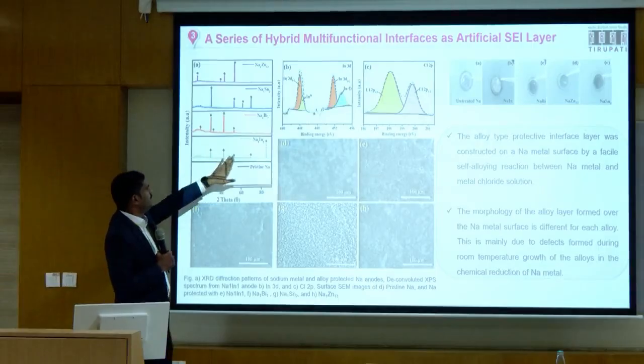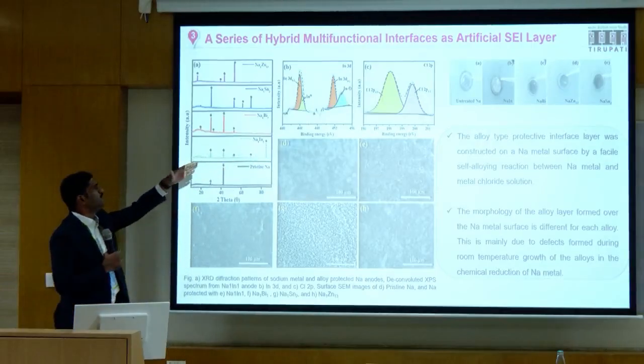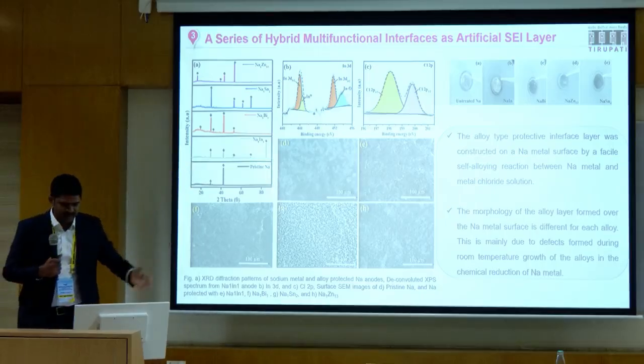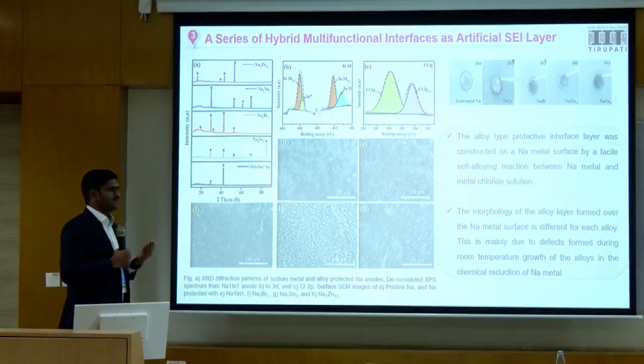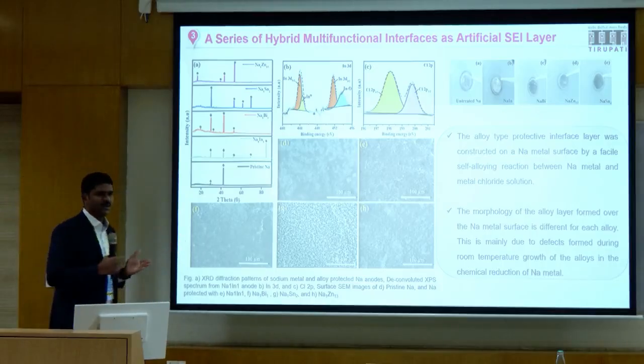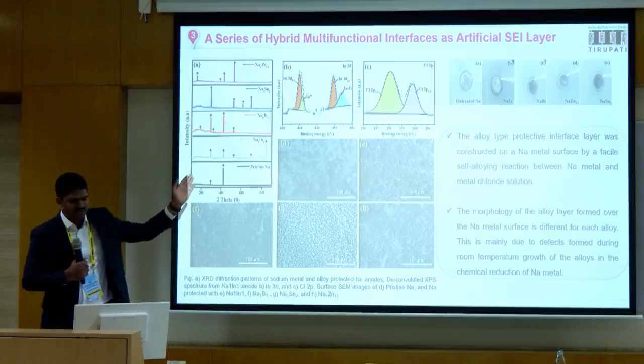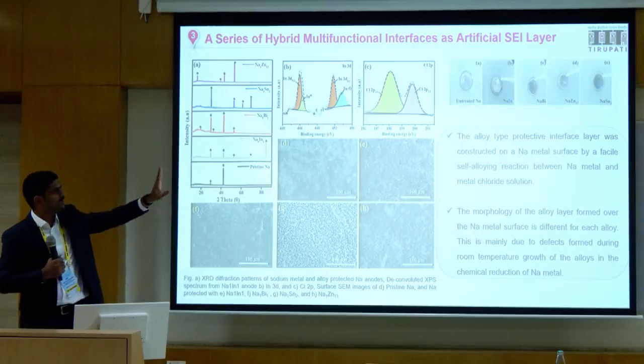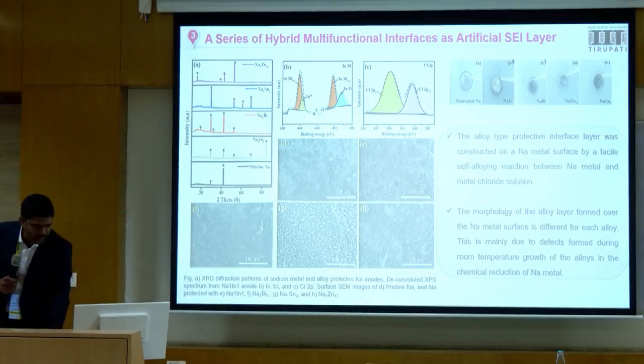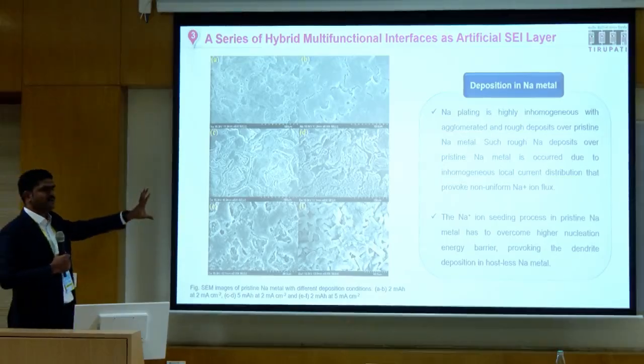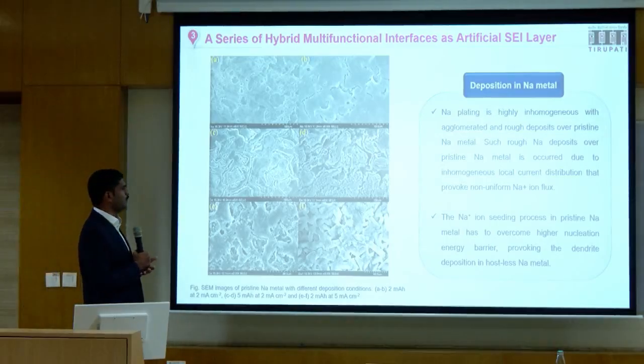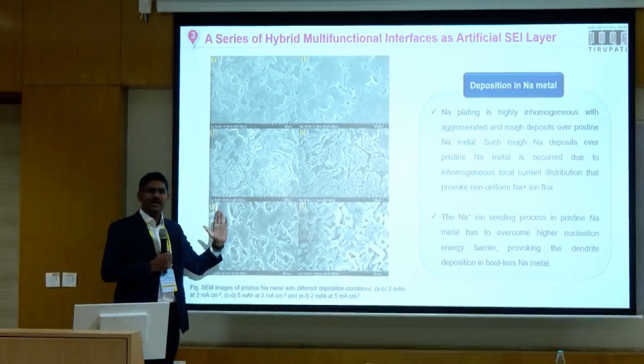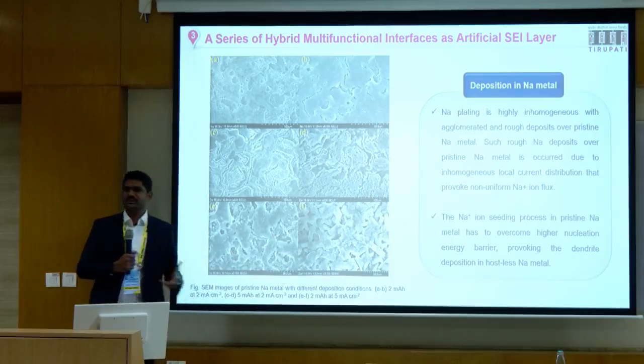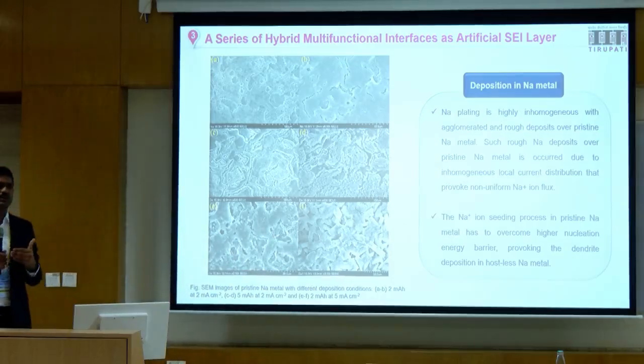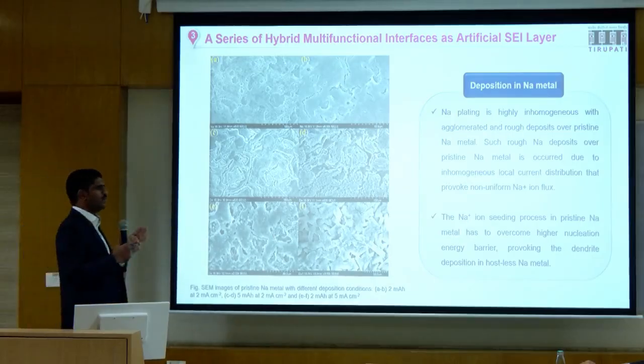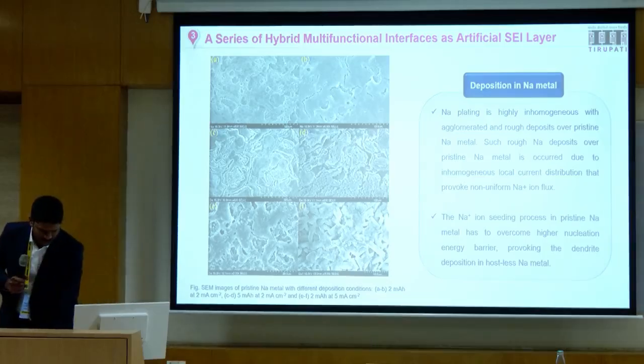We developed sodium-indium alloy, sodium-bismuth alloy, sodium-zinc and sodium-tin. Several alloys were grown with a facile solution-based technology, a simple chemical reaction. You can see in the last figure that the artificial SEI layer based on these alloys was nicely grown over the metal. And what you observe here is that when such artificial SEI layers are not grown, as in the previous discussion, a lot of needle-like structures grow over the sodium metal, which penetrate between the anode and cathode, thereby internally short-circuiting your battery.